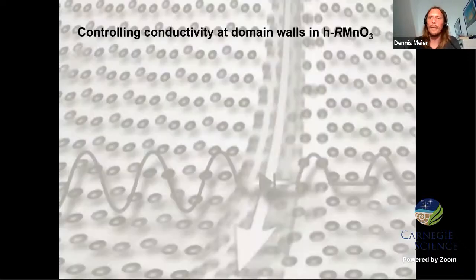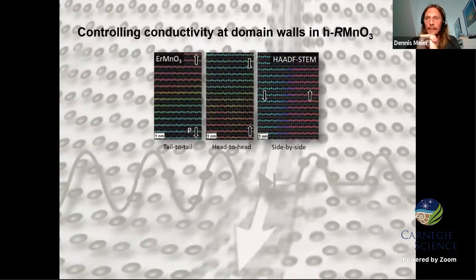As I said, it's all about controlling conductivity now. And what I've already shown you is that we have three fundamental types of domain walls in this material: tail-to-tail, head-to-head, and side-by-side, which are named with respect to the direction of the polarization arrows and how they change across the wall. The idea now is, if we have different charge states, we can expect different ferroelectric responses, or also different carrier accumulation at these walls.